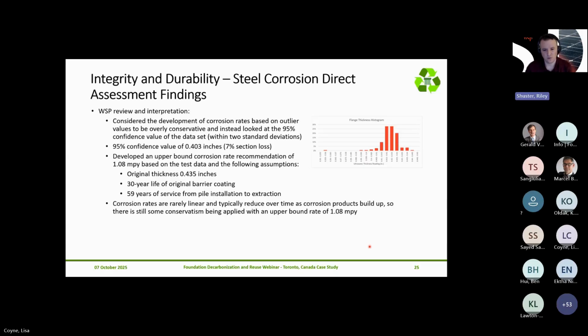So for our purposes, specifically with driven piles that are not subject to the same constraints as something like a pipe that might carry fluid, we would consider the development of corrosion rates based on an outlier value to be quite conservative. And instead, we would focus on the 95% confidence value for the data set. In that case, that value refers to the point within 2 standard deviations. And on this project, that amounts to approximately 7% section loss. So pretty significant reduction over the pitting value that we saw previously.